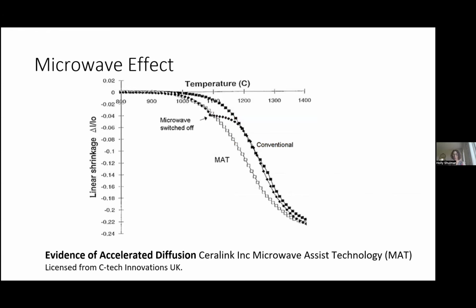Okay, so one thing I want to point out, I talked about temperature being a tricky thing to understand, and there's been a debate in the microwave community for many years on whether microwaves are actually causing an accelerated diffusion, or if it's just that it's hotter there and you're not measuring the right temperature. And from the engineering point of view, well, what works? There is a scientific explanation for enhanced diffusion, and the best one I've seen is on the ponderomotive effect. That's getting into the weeds. But this data is something that convinced me that microwaves absolutely are enhancing heating and diffusion, and it is really the clearest evidence of accelerated diffusion.